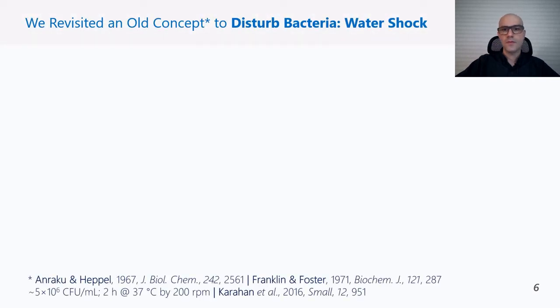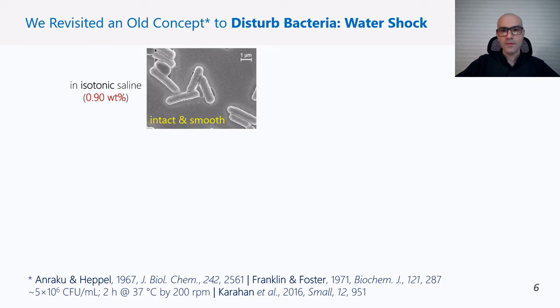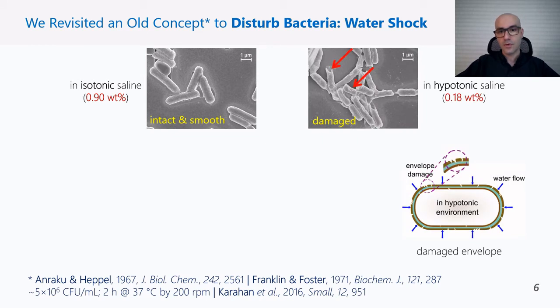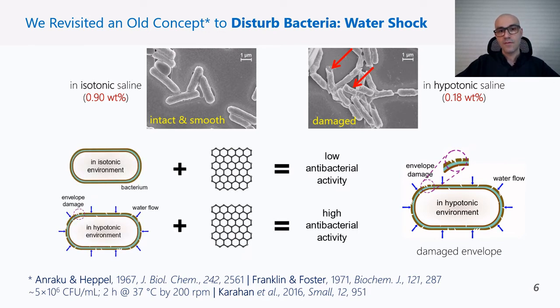And we disturbed the outer membranes of gram-negative bacteria using an old trick, water shock, also known as hypoosmotic shock. On the left, you see happy bacterial cells exposed to salty water that they like. The salt concentration inside and outside of the cells are close. As a result, cell surfaces are intact and smooth. When the salt concentration is reduced, however, some cells burst, and intact cells are also damaged sublethally. Based on this principle, I hypothesized that we could observe higher antibacterial activity if we treat bacterial cells with graphene oxide and water shock at the same time.